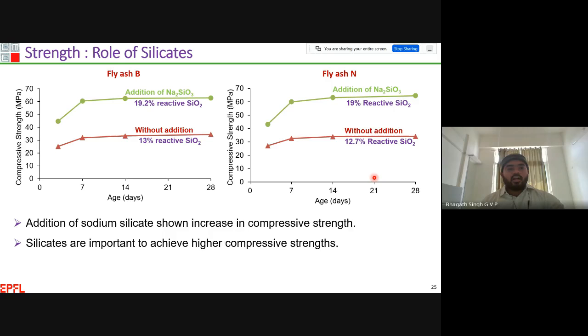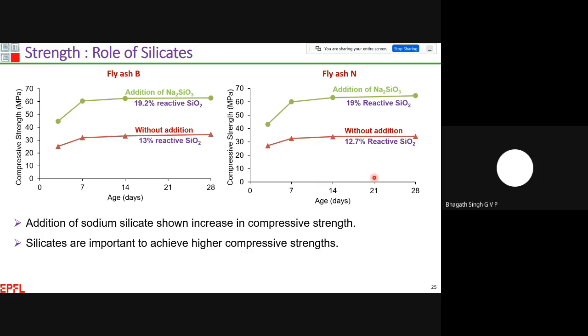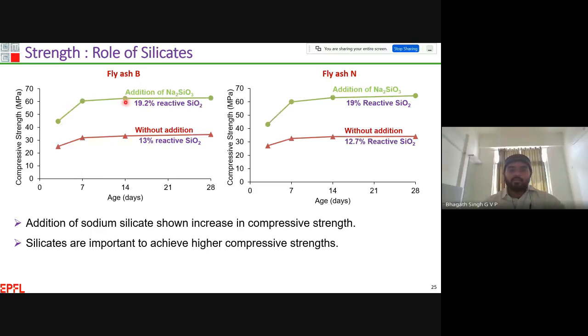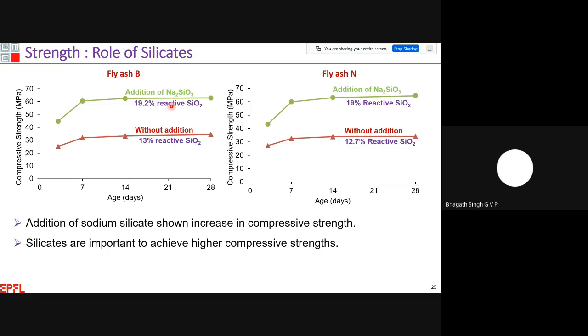And coming to the role of silicates on strength development in fly ash based binders, this is the compressive strength with respect to age. This is for fly ash B and this is for fly ash N. These are the source locations. These are the values without addition of sodium silicate, which has about 13% of reactive silica. Once I increased the reactive silica from 13% to 19%, I can see a significant difference in the compressive strength at any particular time. With 19% of reactive silica, I can achieve about 63 megapascals compressive strength ultimately. But in the case of 13% reactive silica, I can achieve about 32 megapascals compressive strength in the activated system. Due to this, silicates are very important to achieve the ultimate higher compressive strength in the activated mixes.